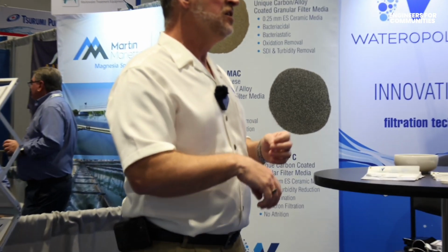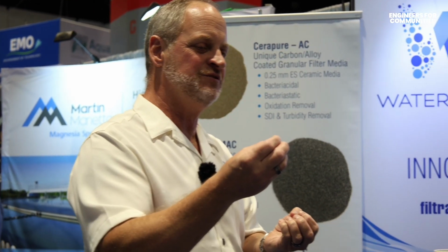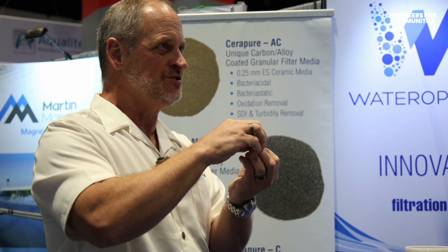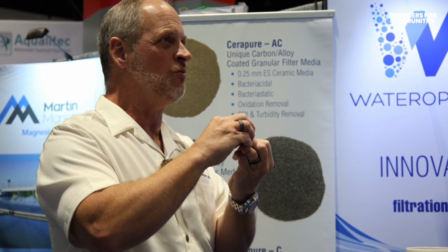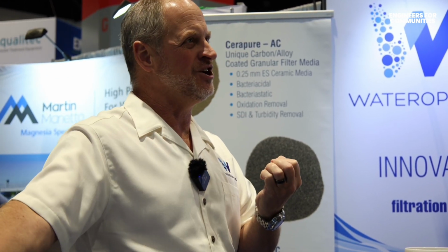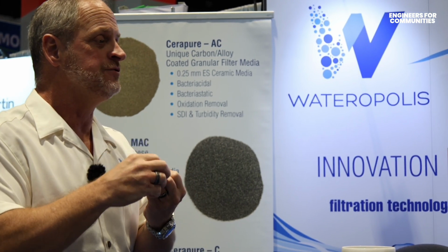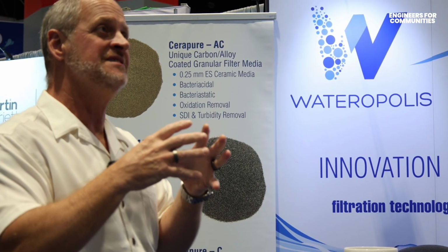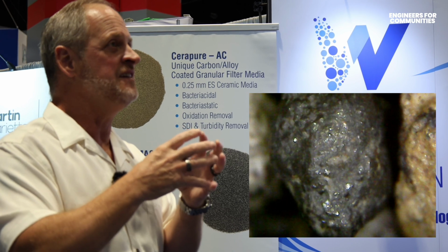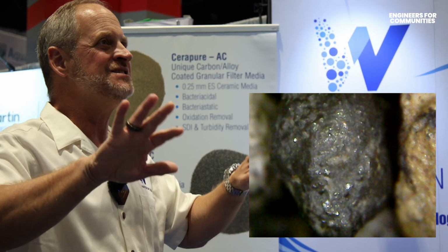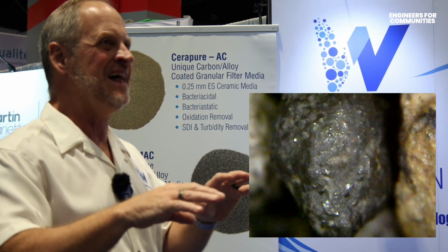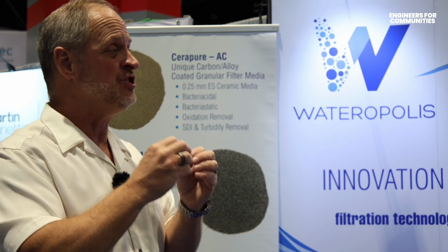So instead, you end up needing a filter media with a manganese dioxide coating, enough oxidation potential to create that crystal formation. And basically what you're doing is taking manganese from the water, creating a loose crystal structure on the filter media until you backwash, breaking that loose and backwashing it off. Over time, filter medias that take out manganese actually grow in size. They develop a manganese coating that never comes off. The inside of your tanks turn black, the inside of your pipes turn black, and that media dimension actually changes